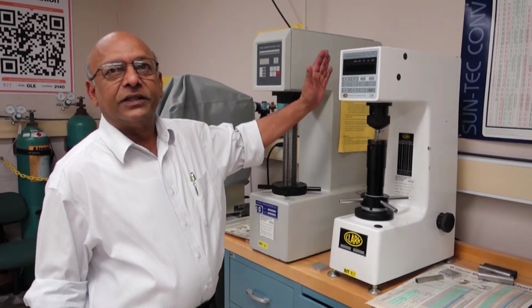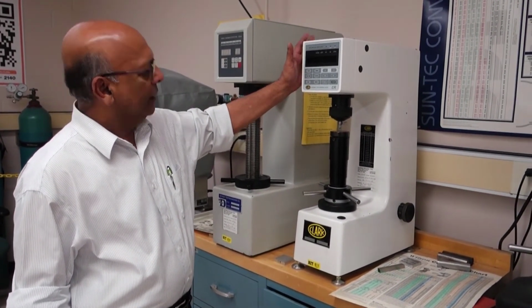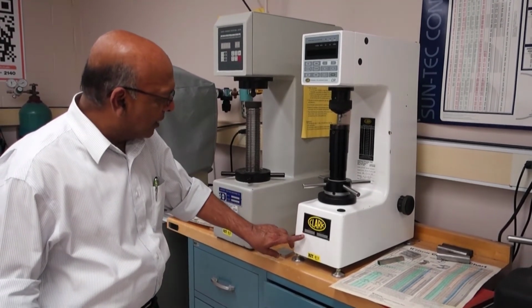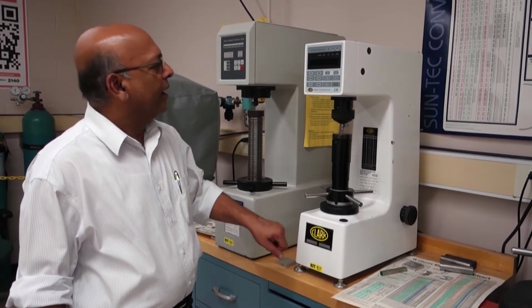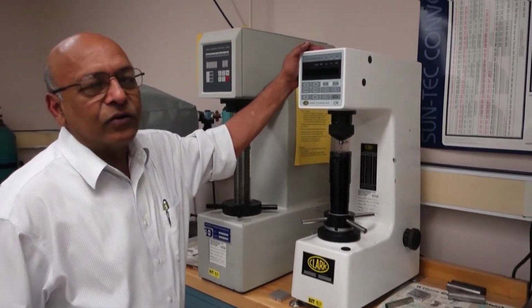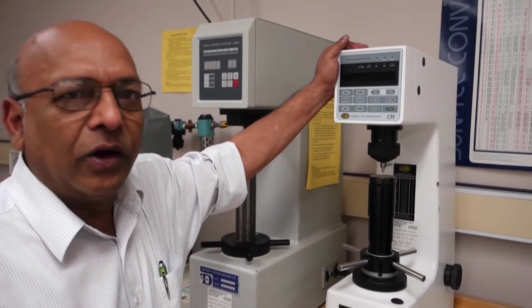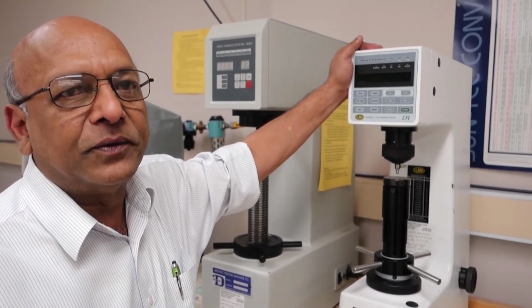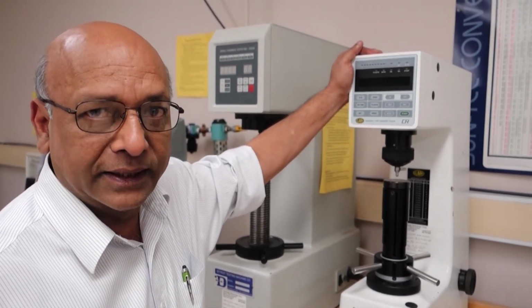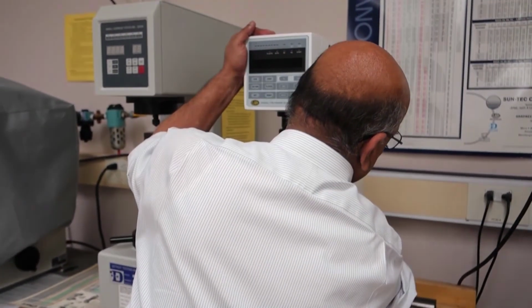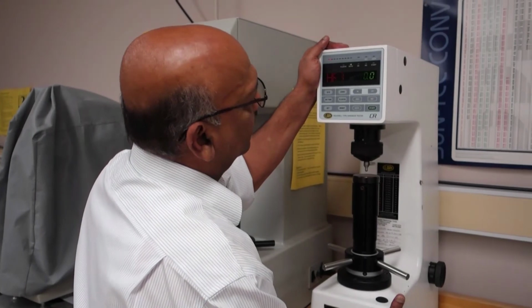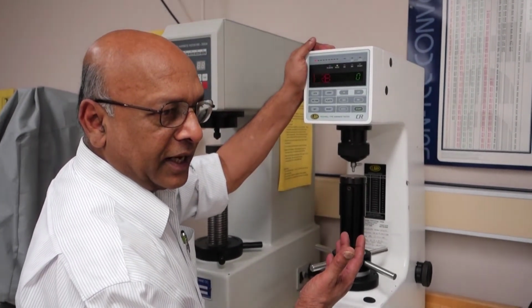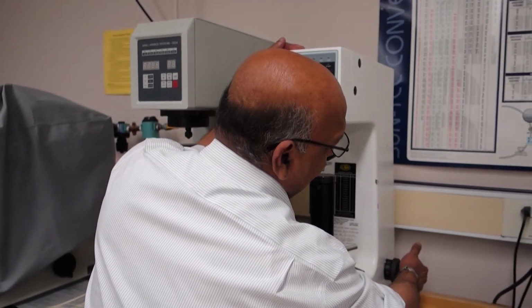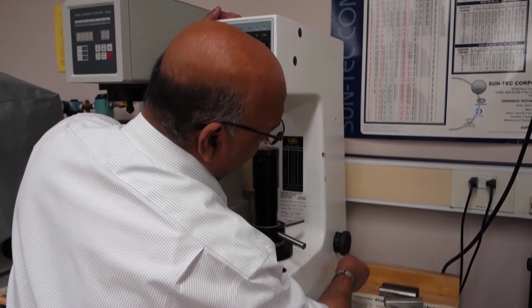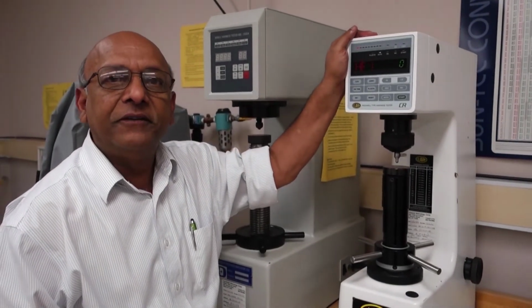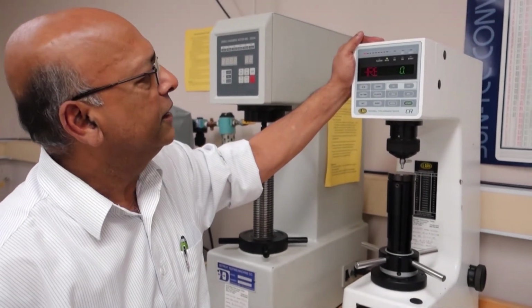Good afternoon, folks. This is our Rockwell hardness tester. It is a Clark model CR3E. This allows us to do both regular Rockwell hardness testing as well as superficial Rockwell hardness testing. I'm going to switch on the machine, which is at the back. It takes about 20 seconds to initialize. We have a load dial here where we can go from loads of 15 kg to 150 kg.